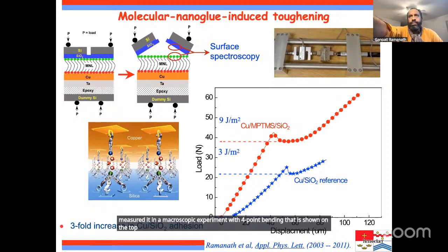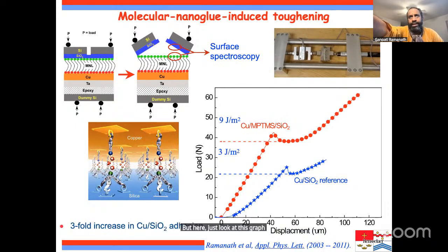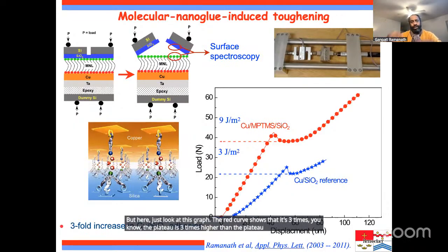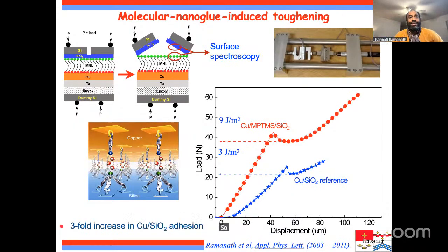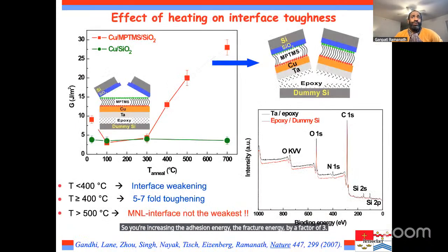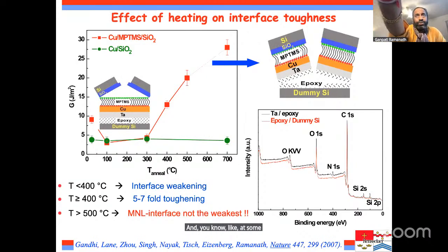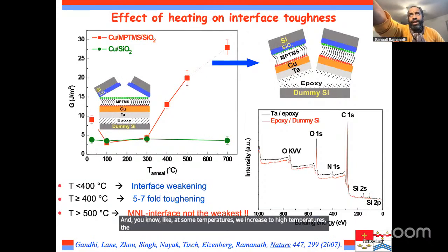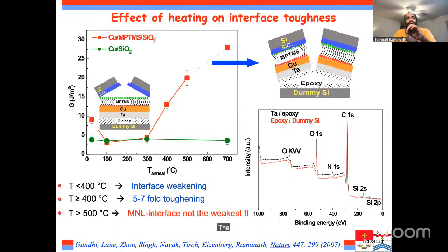top right. But here, just look at this graph. The red curve shows that the plateau is 3 times higher than the plateau in the blue curve. So you're increasing the adhesion energy, the fracture energy, by a factor of 3. And at some temperatures, if we increase to high temperatures, the molecular layer is not even the weakest interface. The epoxy that's holding the dummy sample for experiments is actually breaking. So the results that we found were just mind-boggling in terms of never expected, even when we hypothesized it.